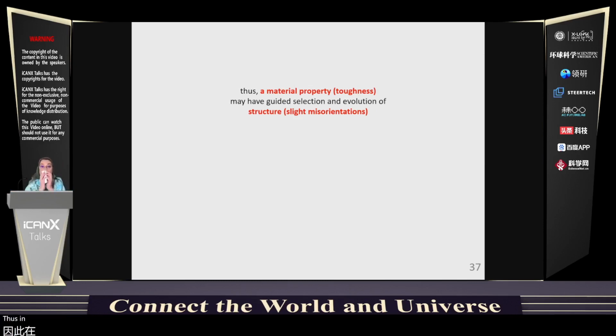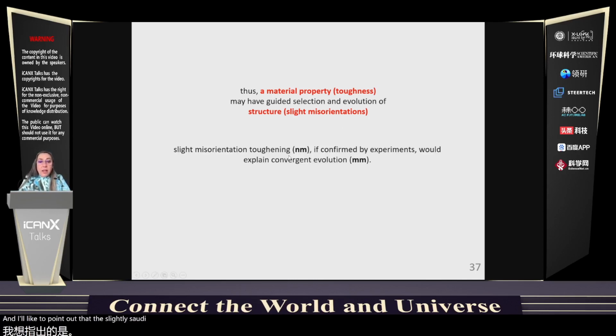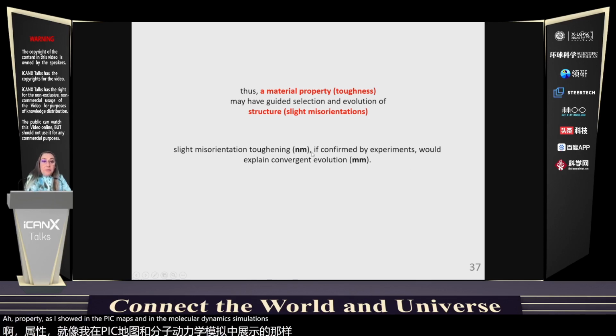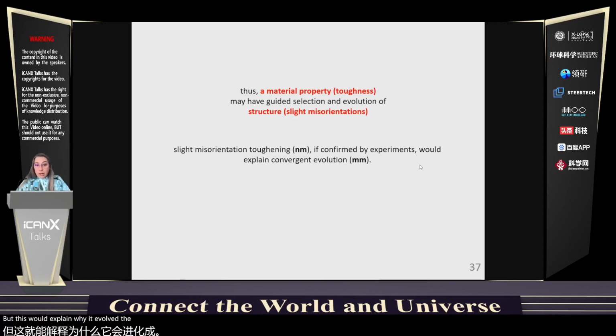Thus, a material property, in this case toughness, may have guided selection and therefore evolution of a structure, a characteristic of the biominerals, in this case, slight misorientation. And I'd like to point out that the slight misorientation toughening is a nanometer scale property, as I showed in the PIC maps and in the molecular dynamic simulations. But if this is confirmed, and I'll show you experiments to confirm it in a moment, this would explain why it evolved convergently. And this convergent evolution is actually a macroscopic scale property that we observe.